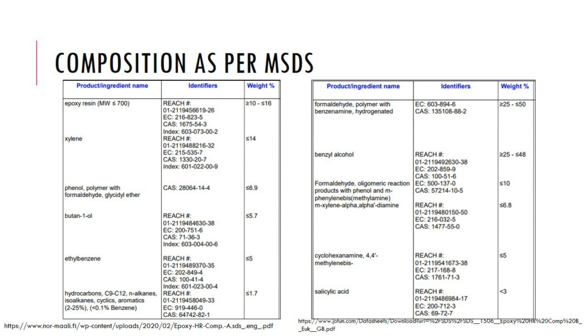If you see here, there are a lot of other contents in component A in addition to epoxy resin, and that's why we need 6.5 parts to get an equivalent number of epoxy resin molecules that can react with the same number of amine hardener molecules in component B.